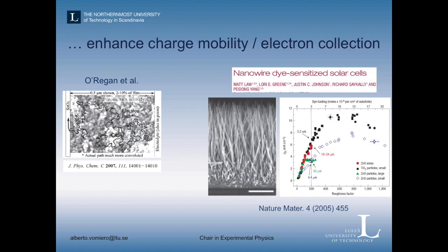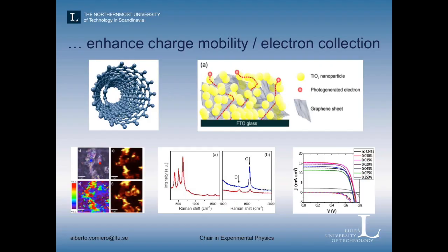technology. And the benefit of nanowires is that once your charge is inside the nanowire, you can straightforward collect it without any hopping process. So the probability of losing this charge is much reduced. And in fact, they were able to demonstrate that by using this kind of wires, they were increasing the photoconversion efficiency. And we tried to do the same using carbon-based materials, either using carbon nanotubes or using graphene sheet.